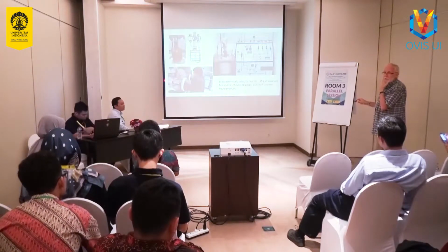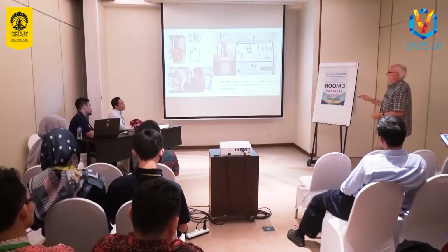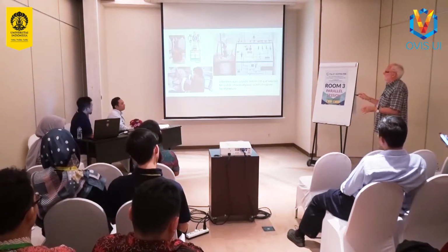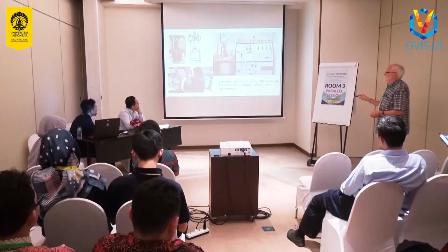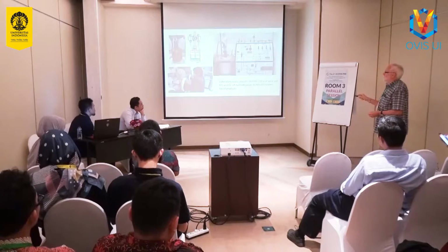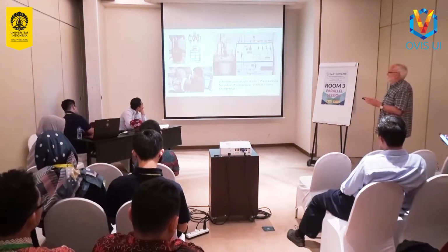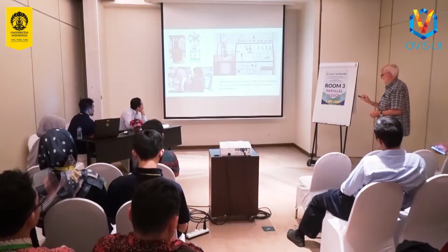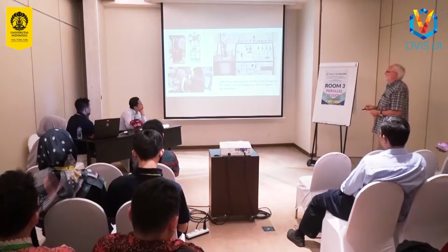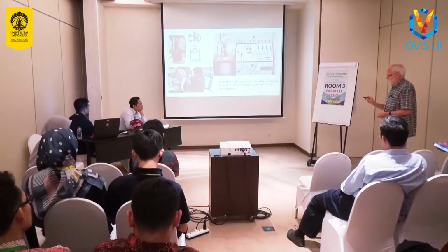So that's slightly cheating. It would be better to use this reactor directly, but the thickness of the stainless steel, for safety reasons, means that we lose a lot of intensity putting the neutron beam through. So we do load it into a can made of aluminium, which is thinner and doesn't absorb neutrons as much as stainless steel. Having done that, we then look at the catalyst at various stages in the MTG process.